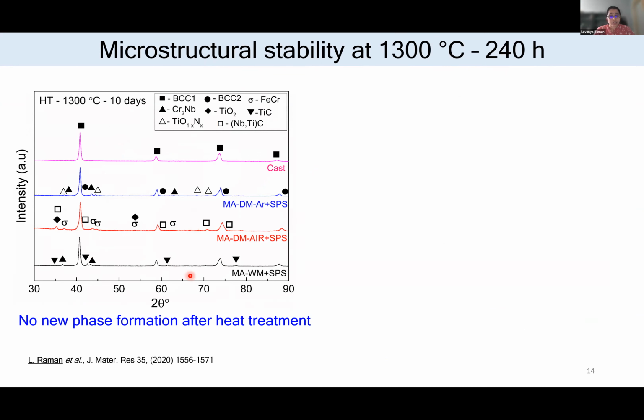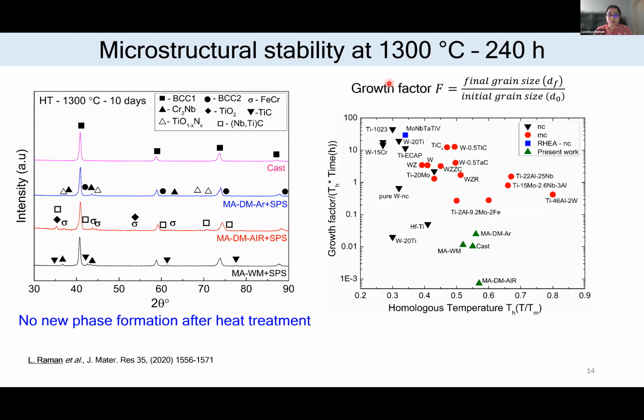From this XRD pattern, we can see that only the phases which were present in the as-synthesized condition are retained, and we did not observe any new phase formation. And also from the EBSD analysis, we estimated the grain size. So the structural stability is shown here.